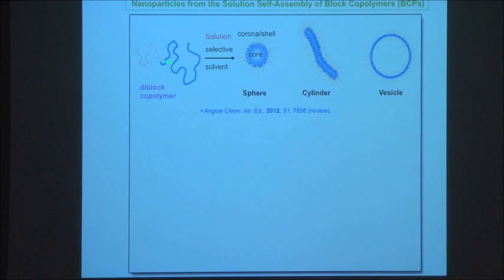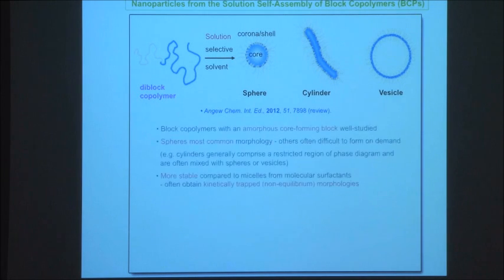So this has been very well developed where the two blocks are organic blocks, and in particular where the two blocks are amorphous. And what's known in virtually all cases where you take block copolymers of this type is they tend to give you spherical micelles. In some cases you can get other structures such as cylinders or vesicles. It's quite difficult to predict which structure you're going to get. Normally you get spheres, but if you want to make cylinders, it's very difficult to dial in the formation of cylinders into this block copolymer.